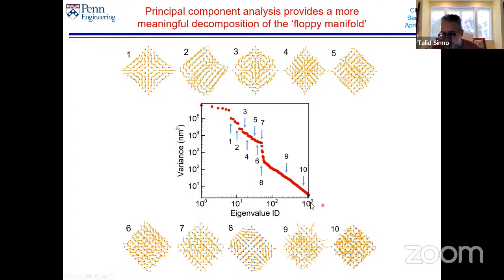So this is, again, all 3,000 modes, or I guess this is a slightly smaller crystal, that was 1,100 modes. You can see up here there are 6 very large amplitude modes that correspond to translation and rotation. And then you can start looking at these large variance modes, and you see that, in fact, they do correspond to very well organized transformation pathways. This is like the Bain transformation. This is some combination of Bain in 2 directions, and so on.